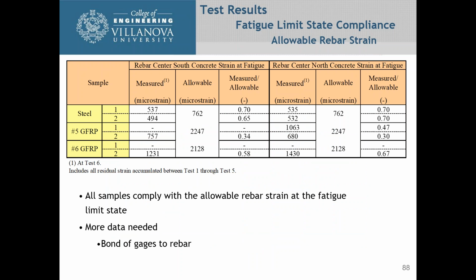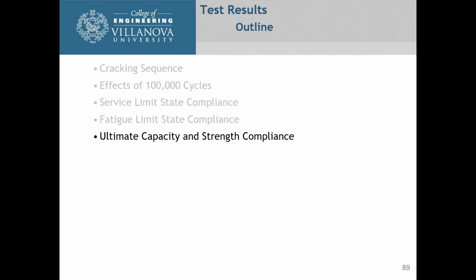So as a summary of the information we were able to get, you can see that the measured divided by the allowable was well within compliance for strain on the rebars during the fatigue limit state. We have to try to figure out a better way of bonding these strain gauges to the rebar without damaging the rebar. So that is one thing that we're looking at right now.